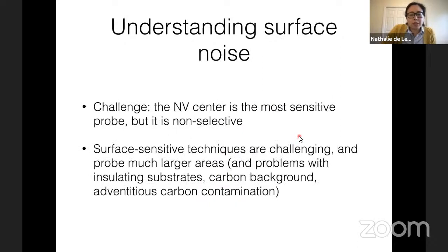So what we set out to do about 4 or 5 years ago was figure out how to understand this surface noise and try to use microscopic understanding to mitigate these problems. The challenge here is that the NV center is a very sensitive probe and it looks at its local environment, but it's very non-selective in that all it can tell you is, I'm seeing a noisy environment. Maybe you can do a little bit better and look at the spectrum of the noise, but it doesn't really tell you anything about the microscopic nature of the noise that you're looking at.